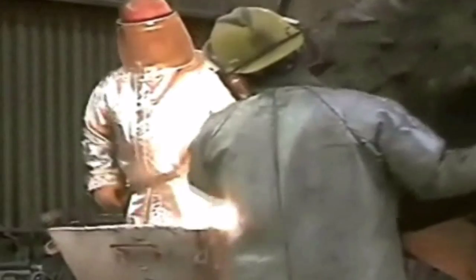At the correct temperature, the shell metal is poured first, and after an appropriate time, the softer, tougher core metal is poured, giving the desired fine-grained bimetallic structure.